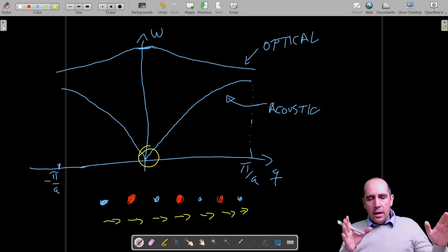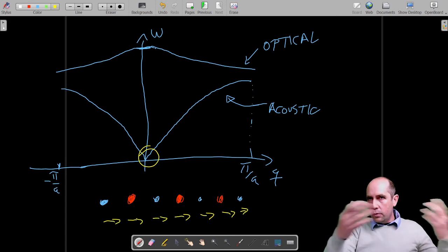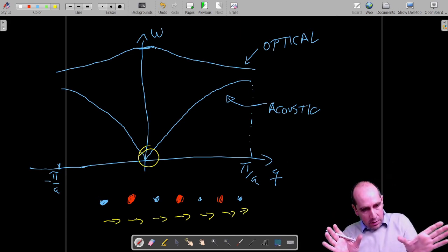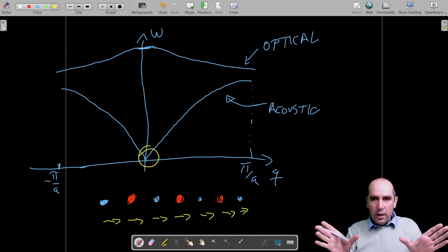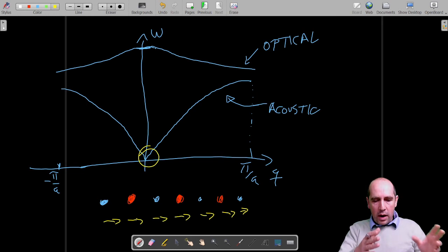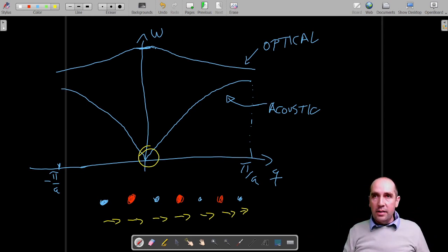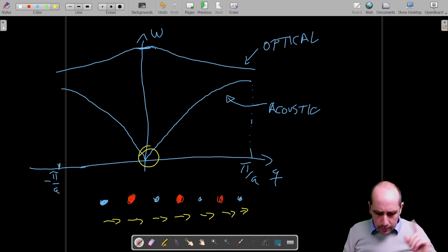Of course, if you go to one full wavelength, which is many thousands or many millions of atoms, you will have a piece of the lattice moving in one direction and the other moving in the opposite direction, and so on. But basically, these are waves that are very long compared to the spacing between the atoms, and locally they all look as if all the atoms were vibrating in phase.